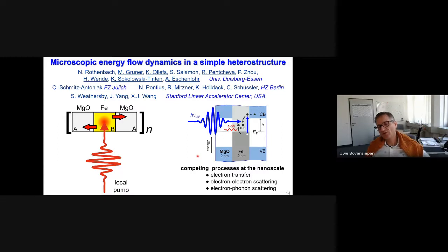Let's look how this translates into the energy dimension. So we have here iron. Iron is a transition metal, so we have a Fermi level, and this is where we absorb the light. We use here UV light of 266 nanometer because we want to reach the conduction band of MgO. So in principle, we have sufficient energy to inject carriers into the conduction band of MgO and overcome this energy transfer barrier delta. However, there's a competing process, which is electron-electron scattering, which I've mentioned earlier, which happens in iron, and then subsequently there could be electron-phonon emission to transfer the energy into the adjacent material.